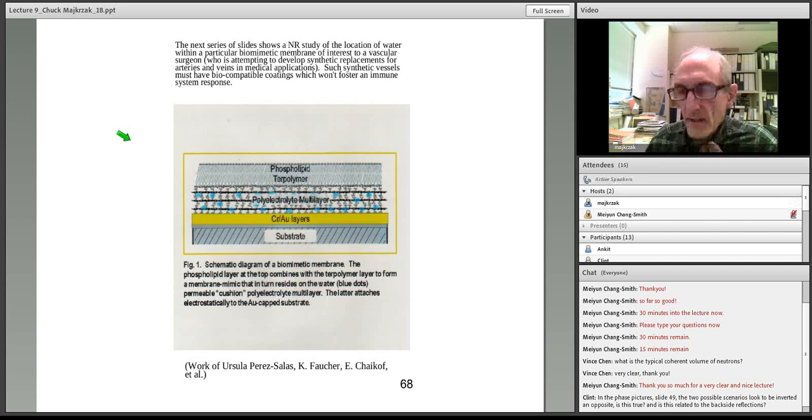Actually, you're right. In the particular case that I showed for the titanium oxide, titanium film on silicon, those are symmetry-related profiles. And this is one danger always that you will have, because when you measure just the reflectivity, you can't distinguish front to back. You can reverse it, and you can't tell the difference. But there are more insidious changes that can occur that you might not expect that will give you ambiguous results,